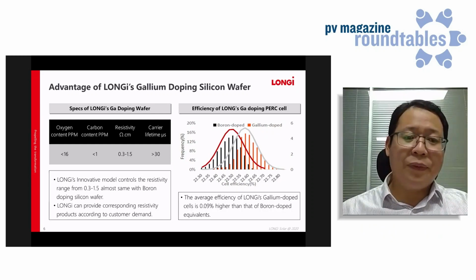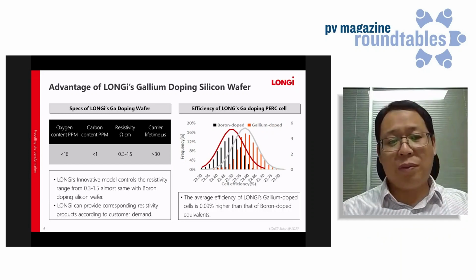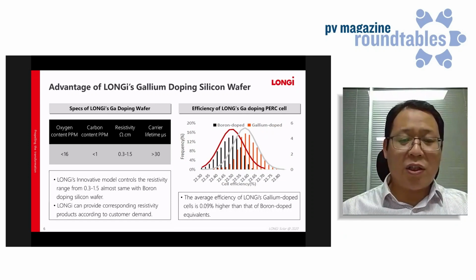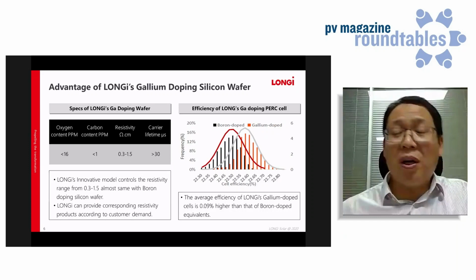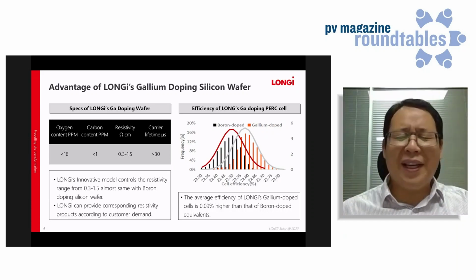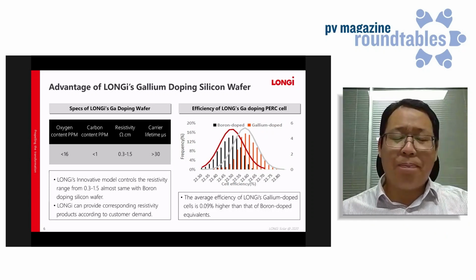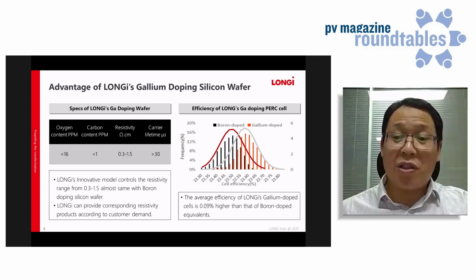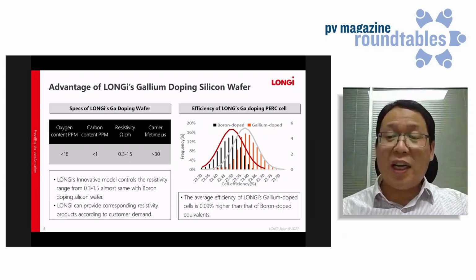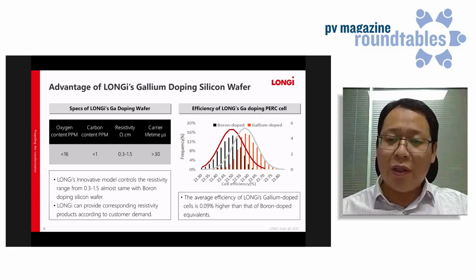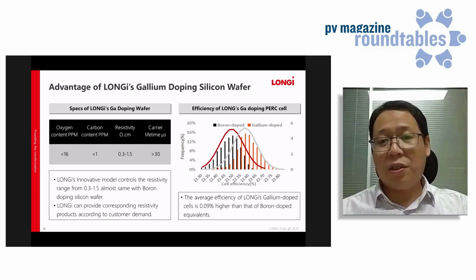The range is from 0.3 to 1.5 ohm, almost the same as boron doping silicon wafer. So we can provide corresponding resistivity products according to the customer's demand. Also for the cost of the gallium doping wafer, we get almost the same cost compared with a boron doping wafer. So we are selling the wafer at the same price to the industry. We get some very good feedback from our wafer customers. Not only is the degradation lower, but also the cell efficiency is a little bit higher. You can see it in the picture on the right side: if we use gallium doping wafer, we get higher cell efficiency, about 0.09% higher than the boron doped wafer.